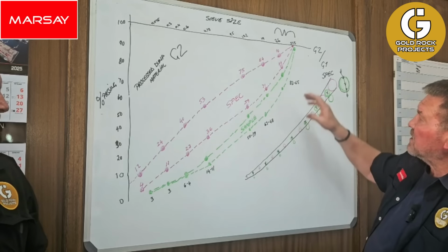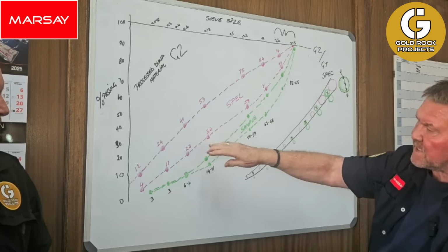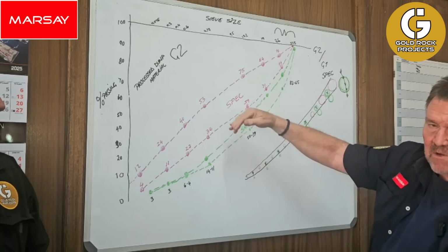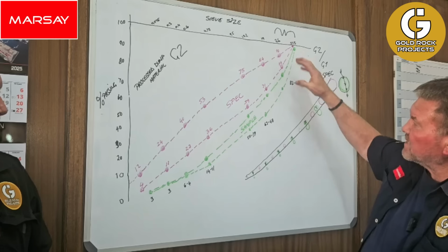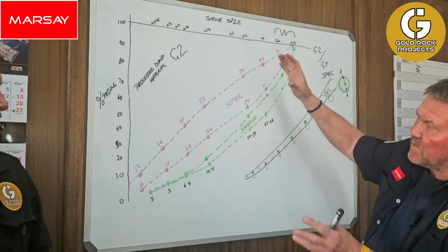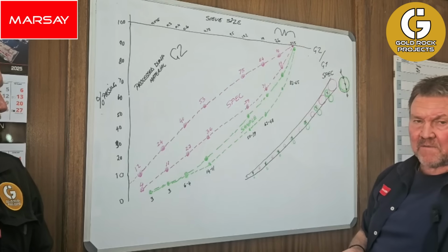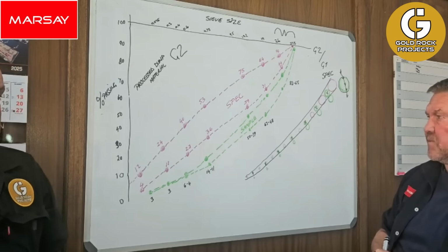And that is one of the ideas that we could take a coarser material, crush it, add it to your material, and resample again to see where actually the spec is sitting at the moment. And from this, you can actually decide, right, crush the coarse, put it in there, or take the volume of the dump, process it by itself, and see wherever the grading comes out. So it all goes about sampling.